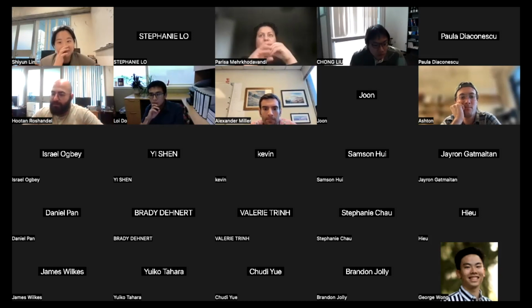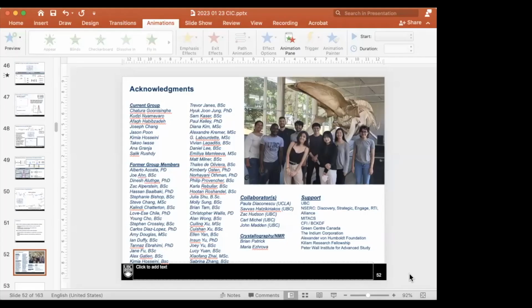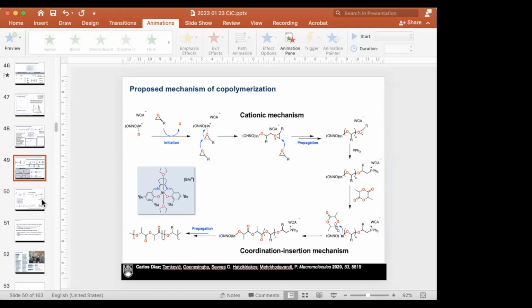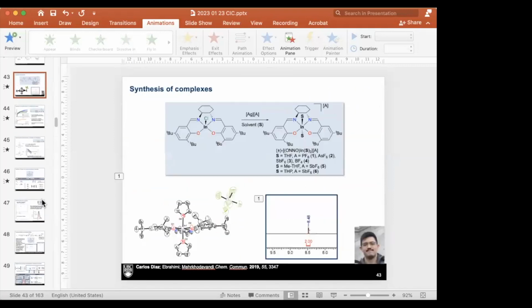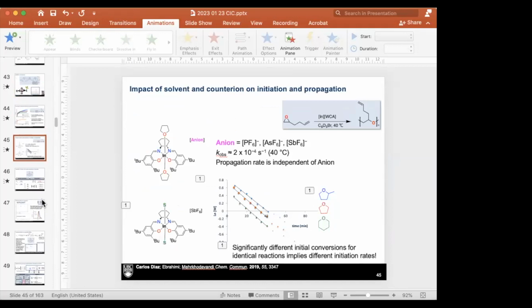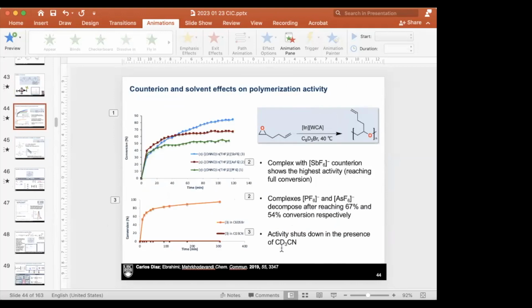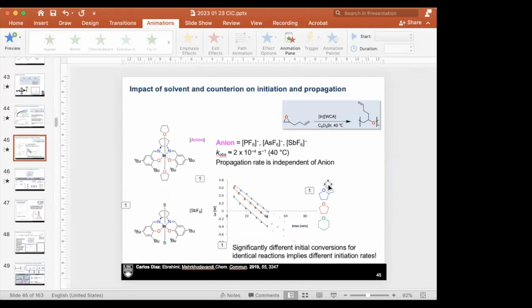So remember that for that system. So let me share my screen again. The thing that really mattered in terms of reactivity, because I know that I sped through this, but the very first thing that needed to happen was a solvent coming off, right? So there's definitely whatever we put in there. If it was a strong donor, if you put something like acetonitrile in there, it just shut down the reactivity, right? And if you put something that's too much of a donor, if you can tune very much what that group would be, it would really affect the rate of reaction.